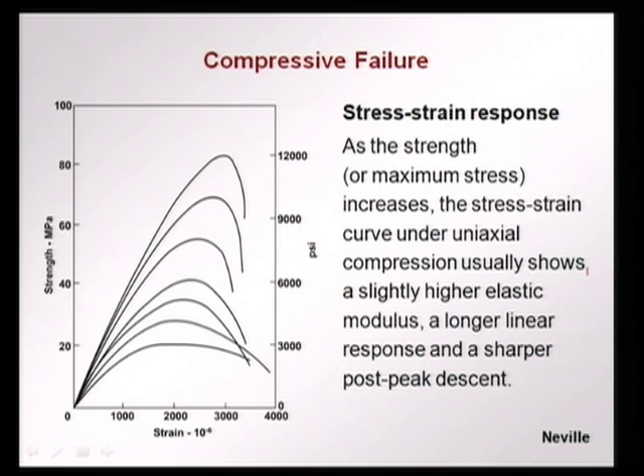This stress strain response varies from one concrete to the other, and we find that as the concrete grade increases or the concrete strength increases, some typical aspects change. First of all, as the strength increases, say from a 20 megapascal concrete to an 80 megapascal concrete, the initial slope increases but not at the same rate. There is a higher initial slope but not proportional to the strength. However, the linear elastic slope or the elastic modulus increases with strength. So, you get a stiffer concrete as the concrete strength increases.